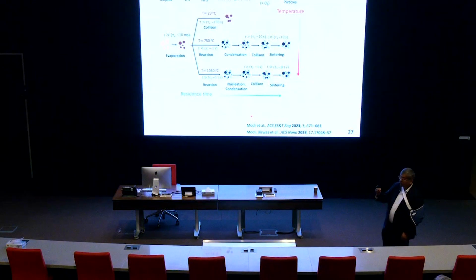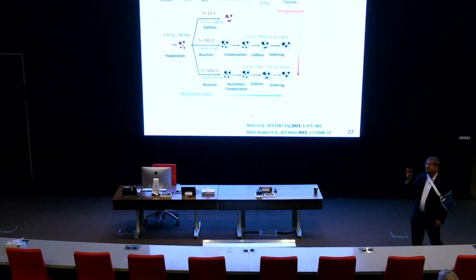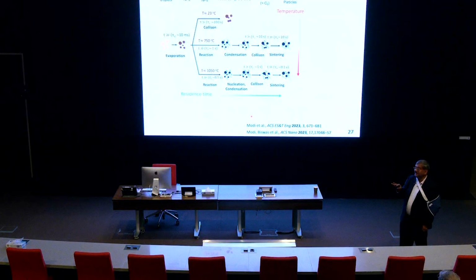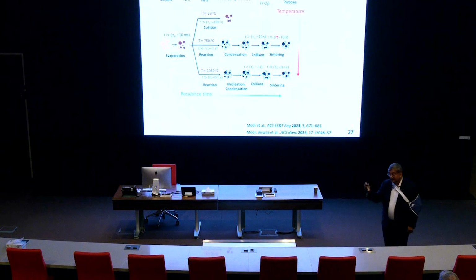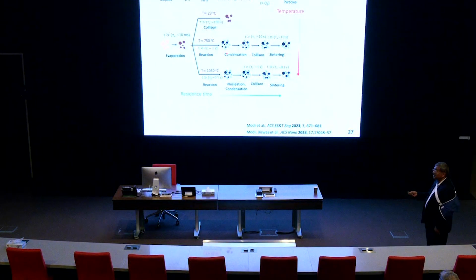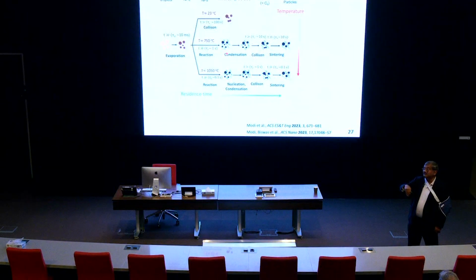Yes, so very good question. I need to be beyond a certain temperature to ensure that it is a pure carbonaceous material, right? And we do the analysis to figure that out. So that's why you see I have two temperatures here in some sense. So at this temperature, it's completely pyrolyzing all the way to carbon, whereas these are more mixed species and things like that, right? And you also have the reverse. At a slightly intermediate temperature, you might condense some of these vapor species back onto the structure, even if they might come out as per your kinetics evaluation, but then they recondense and you end up in the structure. But at a higher temperature, maybe they're getting knocked out completely.